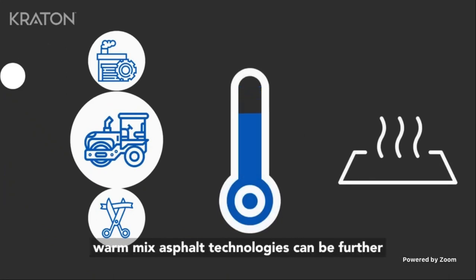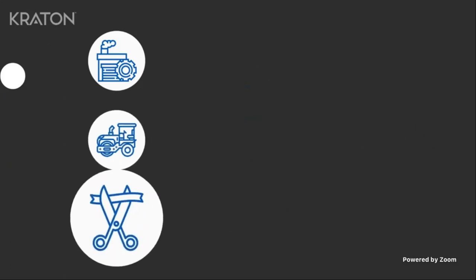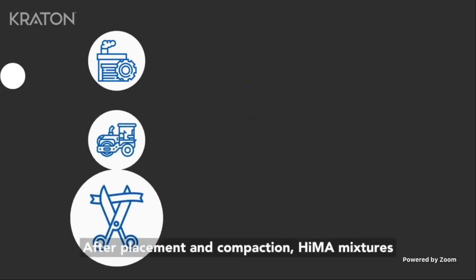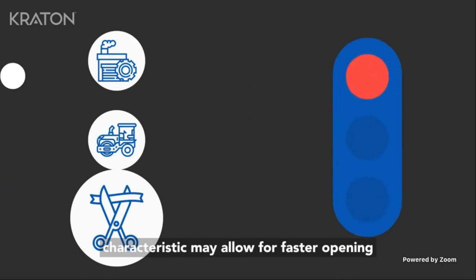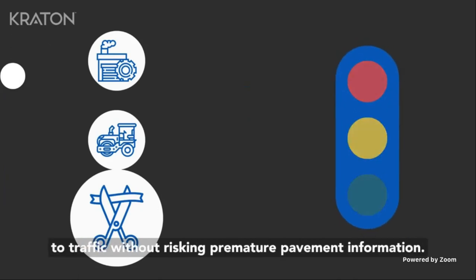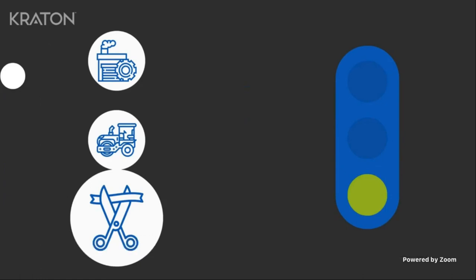The conventional warm mix asphalt technologies can be further used to improve the mixture workability and reduce the production and paving temperatures. After placement and compaction, HiMA mixtures reach the conventional asphalt stiffness at a relatively higher temperature. This characteristic may allow for faster opening to the traffic without risking premature pavement deformation.